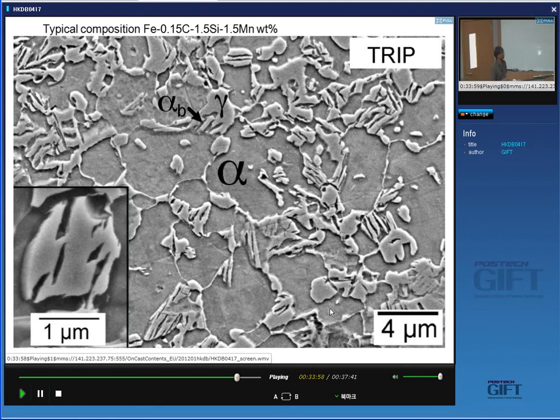And it looks something like this, and almost all TRIP-assisted steels have roughly this composition: 0.15% carbon, 1.5% silicon purely there to stop cementite precipitation during the bainite reaction, and 1.5% manganese to give you hardenability. About 70% of the microstructure is just allotriomorphic ferrite, okay? And the remainder is transformed into a mixture of bainite and carbon-enriched retained austenite. And that retained austenite typically has a carbon concentration in excess of 1%.